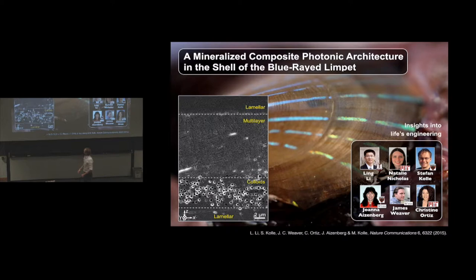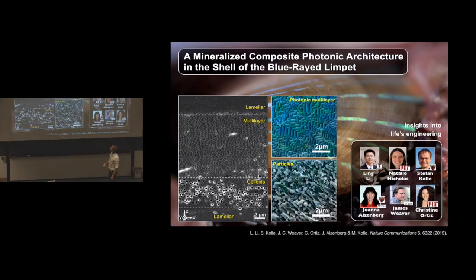And for these features then, Ling took a focused ion beam microscope and took out a thin slice that he put into a transmission electron microscope. And that thin slice shows in very unique beauty what this structure is that creates these blue colors. It's a layered architecture of calcium carbonate lamellae. These calcium carbonate lamellae are spaced by a very distinct spacing of about 190 nanometers. The lamellae are about 110 nanometers thick. And it creates an interference. It's like the effect that you know from an oil film on water, except for now you have many oil films, calcium plates spaced on many water films. So it's an amplification of a reflection and then a constructive interference. It's like an optical filter in a microscope, except for this is in the mollusk shell. The sort of feature near the bottom is interesting because these are particles that are highly absorbing. And it creates those to make sure that the colors that are not blue, the reds, the greens, the yellows, that can transmit through that reflector, through that multilayered structure, get absorbed. So they don't come out again and destructively interfere with, sort of desaturate the color that creates the blue edge.